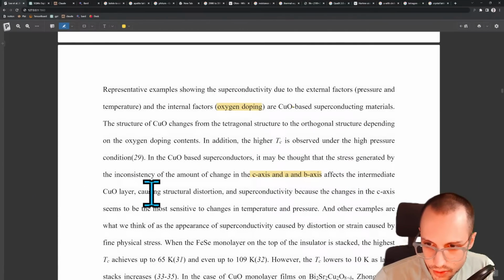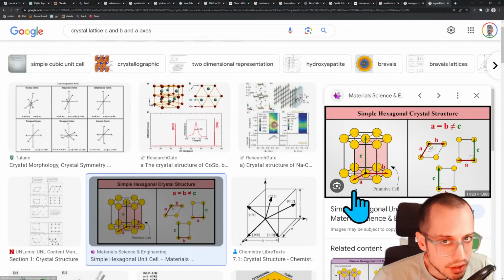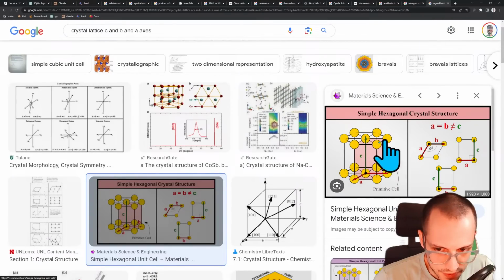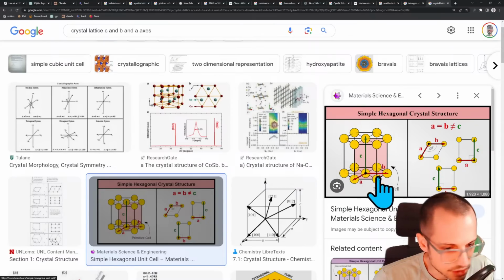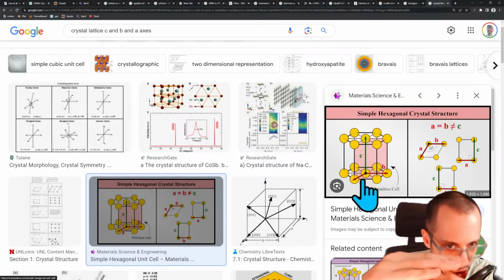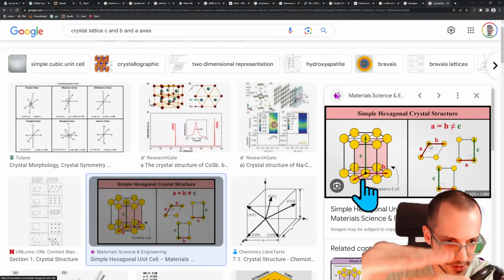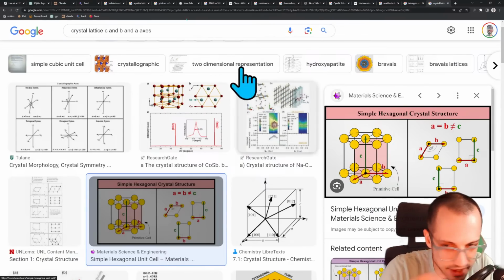It affects the intermediate CuO, causing structural distortion and superconductivity, because the changes in the C-axis seem to be the most sensitive to the changes in the temperature and pressure. Okay, so A and B are orthogonal to C. I don't know if this holds for all hexagonal crystal structures, but let's just pretend that it is. So basically you have sheets like this, and it seems like the C-axis is what's changing when you change the temperature and the pressure. You're basically messing with that C-axis there.